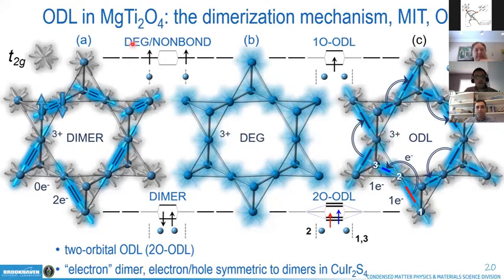Well, in analogy with the iridium system, we have a dimerized system here at low temperature. So this is just basically the pyrochlore sublattice of titanium atoms. These are dimerized titanium atoms, and presumably they carry a charge of 2 electrons, and then there is a different bond charge in between. So the dimer is described like so. In this particular case, we only have 1 electron per titanium, rather than half a hole per iridium in the previous case.